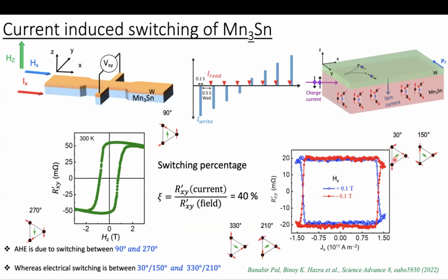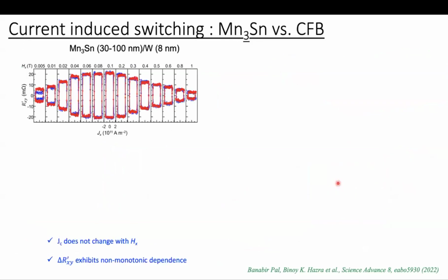And one can see that if you take the projection of this green moment along the Z or minus Z direction, the switching percentage should be 50%. That has been calculated theoretically. And we observe 40%, which is close to the theoretical value. Note that when the bias field is 0, we don't observe any current-induced switching. The switching was 0. This profile shows the current-induced switching as a function of bias field.